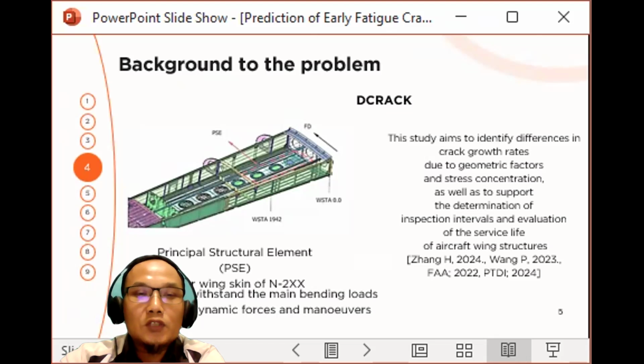To conduct our analysis, we use a software tool called DCRACK. For those who might not be familiar with it, DCRACK is a program specifically designed to predict fatigue crack growth by considering real operational loads. The software requires several key inputs. One, material properties of AL 2024 T351. Two, flight spectrum data. Three, the beta factor. As highlighted by previous studies, the beta factor is critical because even slight change in geometry can significantly accelerate or slow down crack growth. With all this input, DCRACK generates a prediction of how cracks develop over time.